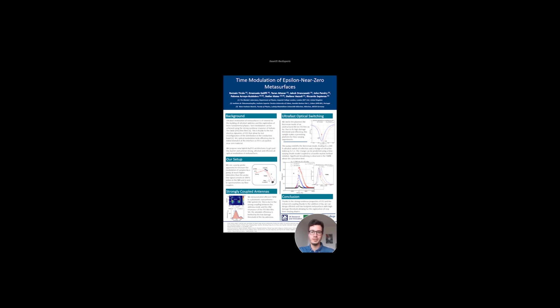The usual limitation in efficiency of these nanosystems is the high index contrast at the interface with the medium. We try to overcome such limitation by depositing gold nanoantennas on top of a 40 nanometer thick film of ITO. The plasmonic resonances of the antennas had strong coupling with the ENZ mode of the nanolayer, and thus we achieved strong field enhancement and ultra-fast change in properties of the medium with that nanolayer with antennas on top.